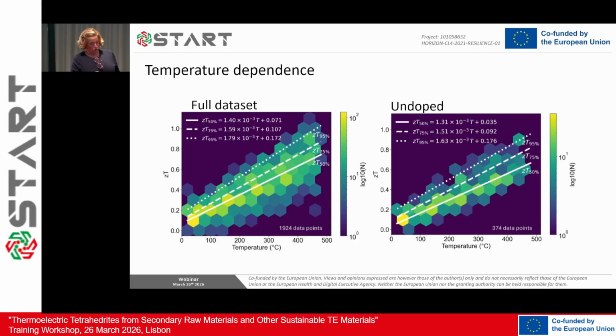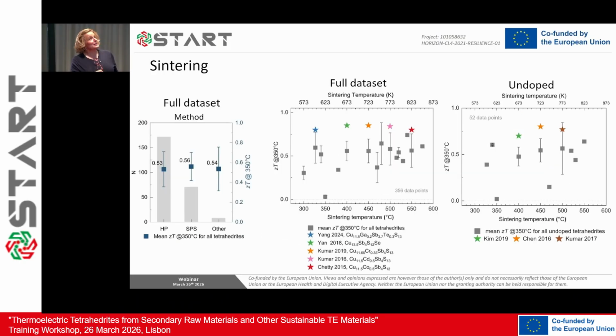So if we do that for all the data set, what we see is that whether you prepare the samples by hot press or SPS or other techniques, which are very few but still there are some, you get exactly the same result. The average is the same and the standard deviation is more or less the same. So there's not so much we can take from the processing method, the sintering method.